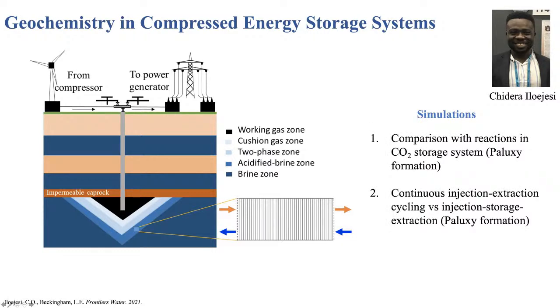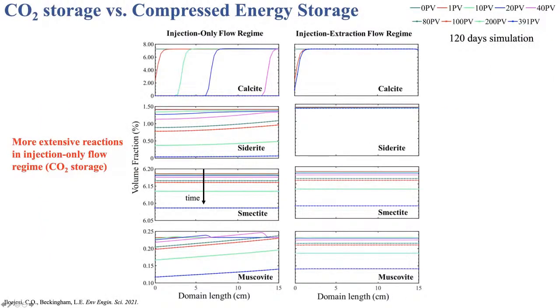The first, we're comparing the reactions that occur for CO2 storage only, and that Paluxy formation we've been talking about. And then we looked at the impact of different operational regimes. So if you're operating with continuous injection and extraction versus cycling injection, storage, and extraction. And this was work that's done by my PhD student, Chidera. So here we have the simulation results and compared to CO2 storage. This simulation's for 120 days, looking at a 15 centimeter domain.